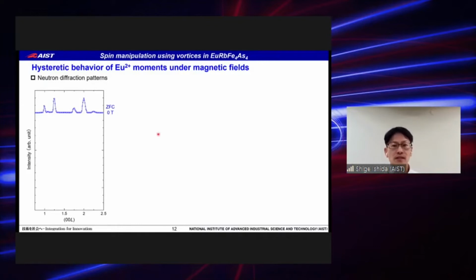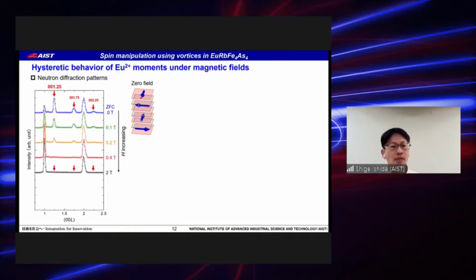The neutron diffraction patterns under zero field cooling condition reproduced the previous report. You can see 00L plus minus 0.25 peaks demonstrating the helical ordering of the europium moment. By increasing the magnetic field, the intensity of these peaks gets weaker and vanishes around 0.4 Tesla. This indicates the europium moments are reoriented and aligned ferromagnetically along the direction of the magnetic field.